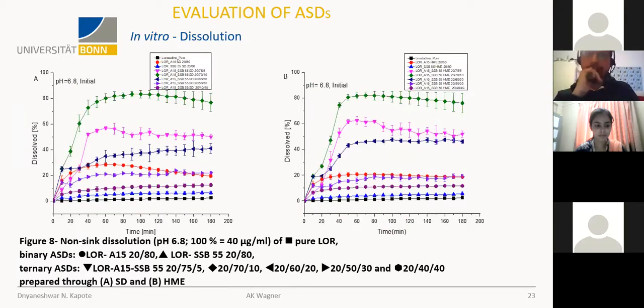Then we investigated the in vitro profile via dissolution using SOTAX. We used non-sink dissolution in order to observe the supersaturation behavior, which is not possible with sink conditions. So the black line on the left side indicates the spray dried formulations, while the right side indicates the hot melt extrusion.